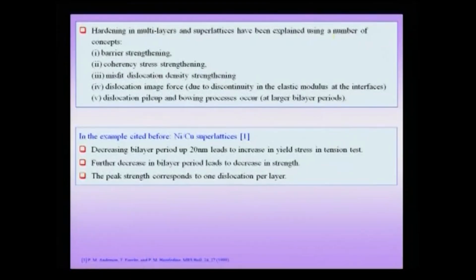So this is a very interesting effect, and if you dwell a little deeper about this nickel copper superlattices, you would notice that a decreasing bilayer period up to about 20 nanometer leads to an increase in the yield stress in the tension test. Further decrease in bilayer period leads to a decrease in the strength. The peak strength corresponds to about 1 dislocation per layer.